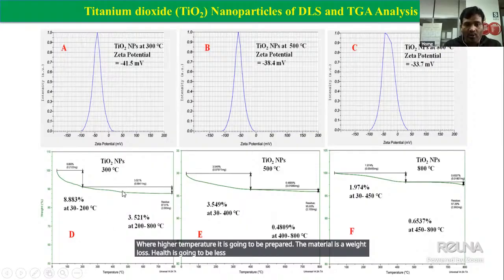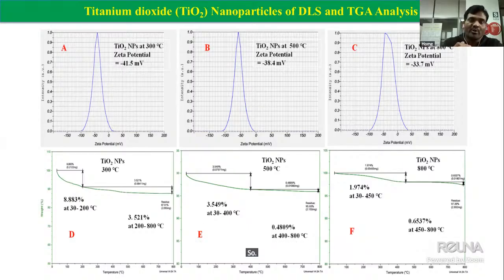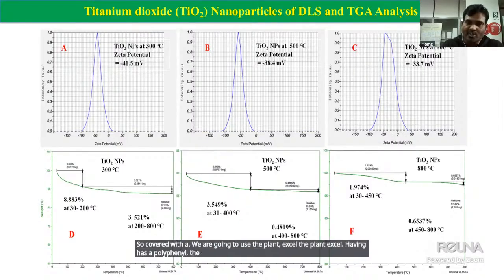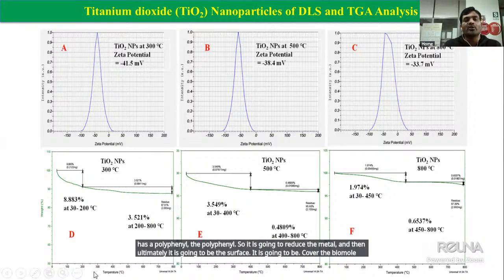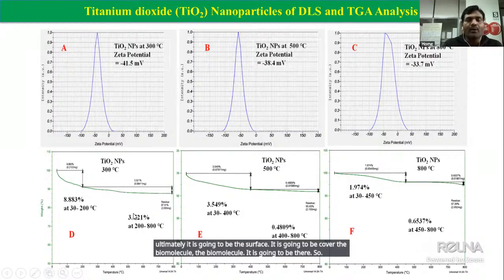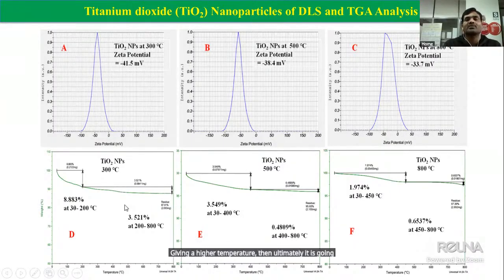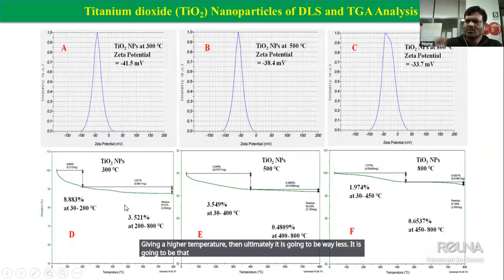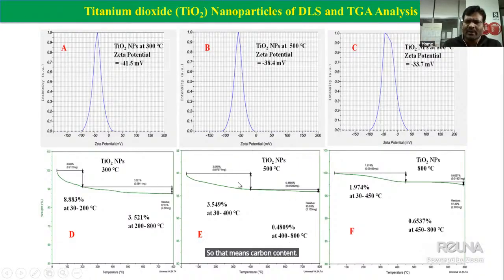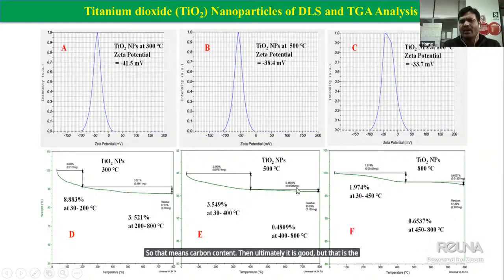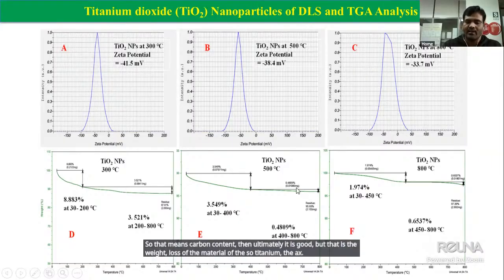So that means at the lower temperature, the nanomaterial is covered with biomolecules. We use plant extract, and the plant extract has polyphenols. The polyphenols reduce the metal ion, and ultimately they cover the surface as biomolecules. The biomolecules decompose at higher temperature, and then weight loss occurs. That means moisture and carbon content, which is the weight loss of the titanium dioxide nanomaterial.